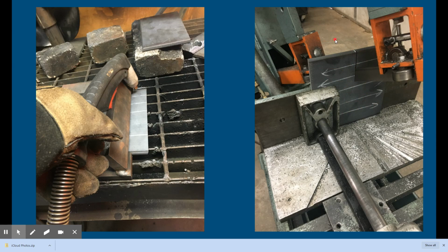It's very important that you cut your bevel across those arrows so that when you bend this, any alignment of the grain... we got to think about grain in metal kind of like we think about grain in woodworking. The grain goes lengthwise with the extrusion, so it's going to be stronger that direction. If you cut it the other direction and the length of extrusion is parallel to your cut, that means when we go to bend these, the weak part of your grain is going across the bend, and it's more likely to fail.